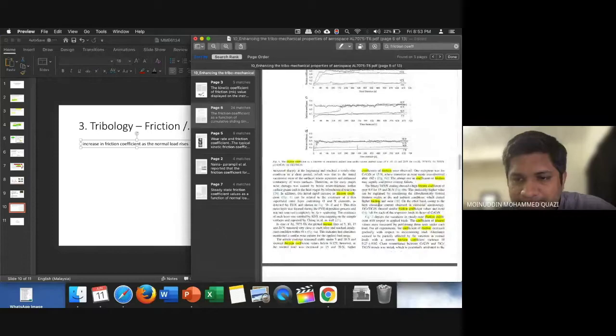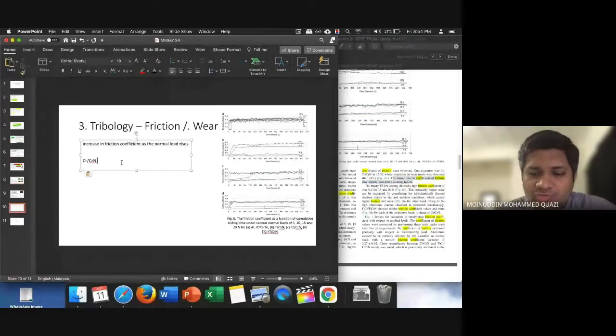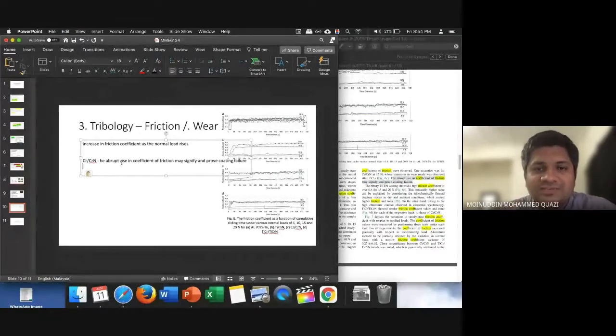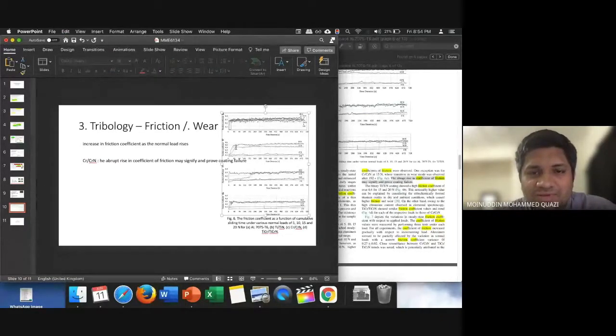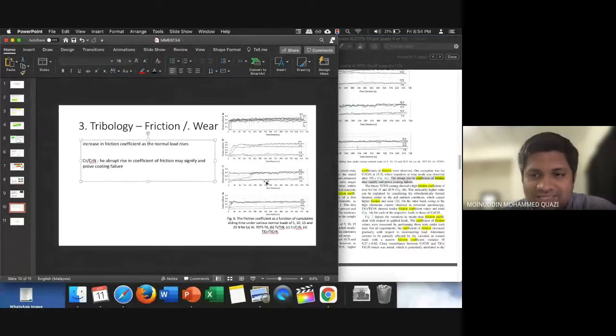So if I go here, then let's say, then you can show that for chromium nitride, it's written here that the abrupt rise in friction coefficient may signify and prove coating failure. So it looks like for chromium nitride, the rise in friction coefficient, as you can see from the graph, the abrupt rise shows maybe the coating has failed already. Okay? So these are some of the characteristics that you have to write and define.